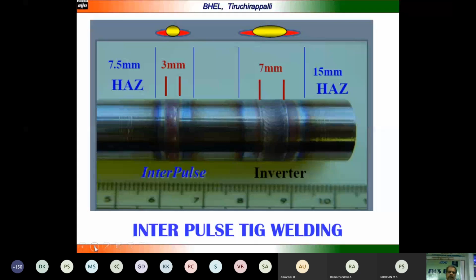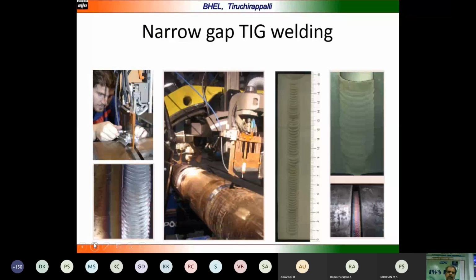The other development happened in the GMAW process. In TIG welding also narrow gap technology is established, and now it has taken us to narrow gap hotwire TIG welding technology, where the hotwire technology and narrow gap technology are combined together as a hybrid process, and the advantages are more. What you are seeing is a narrow gap weld groove, and the narrow gap technology reduces the weld metal consumption and other things. The only difference is the torch cannot be a conventional torch. It has to be a flat torch which has to be designed properly to go deep into the groove, and the welding can be done very easily. The wire feed and the torch both should be a flat type, not of a circular type.